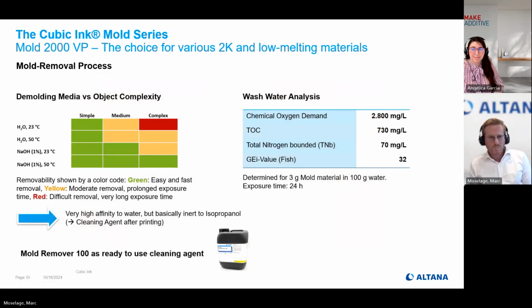So some words again on the mold removal process. What mold type or what properties do you have, or what items can you use to increase the process? As shown in this short video, water, cold water, room temperature water works. What's better? Better is if you have stirring, that's always good. Higher temperature works better. So 50 degrees, 60 degrees, whatever you can make is advantageous. And if applicable, also by using a diluted alkali hydroxide solution, so sodium or potassium hydroxide.